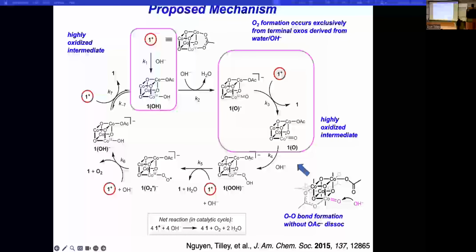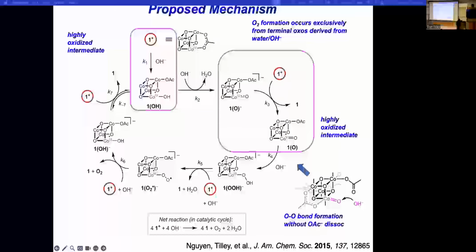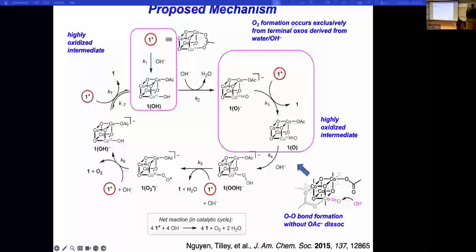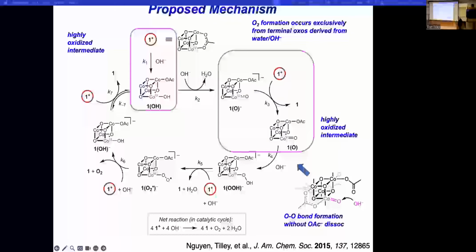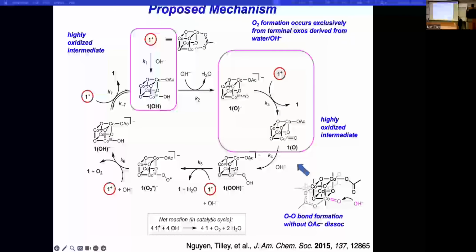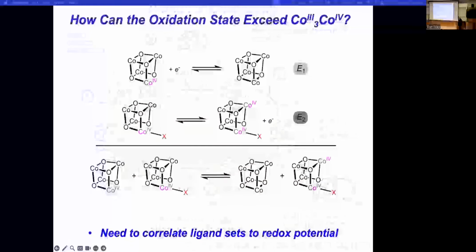The rest of the mechanism is pretty straightforward. This oxo gets attacked by hydroxide. You do some proton-coupled redox events. And you come to this net stoichiometry, which is four oxidized cubanes and four hydroxides give oxygen in that stoichiometric reaction. Now, since acetate isn't dissociated, that attack probably looks a bit like this. So it's attacking in that species where we have the dangling acetate.